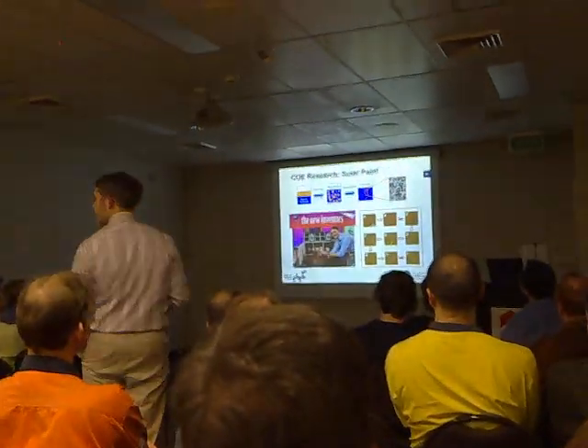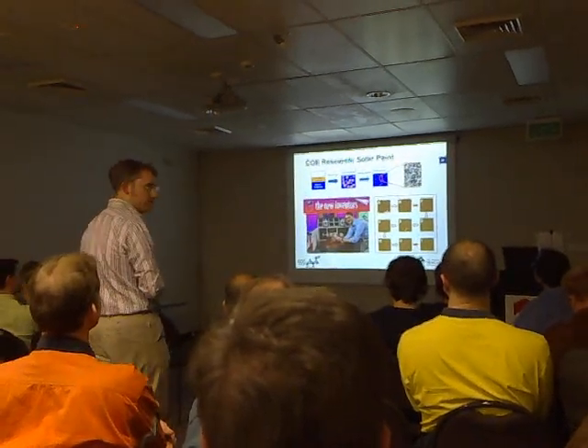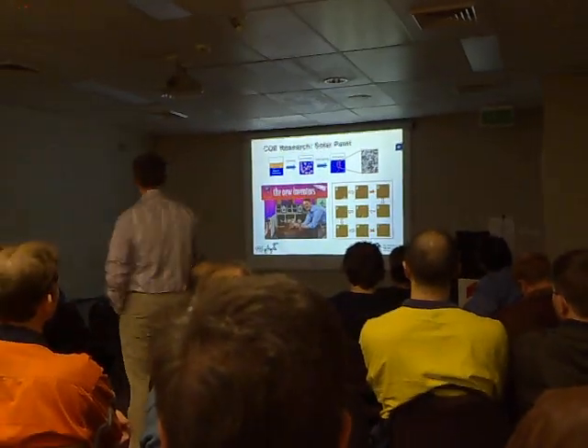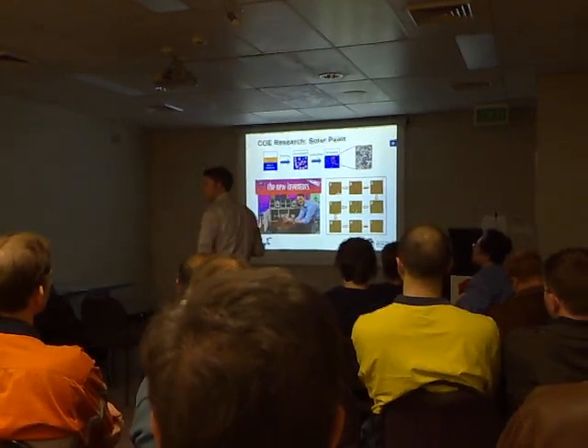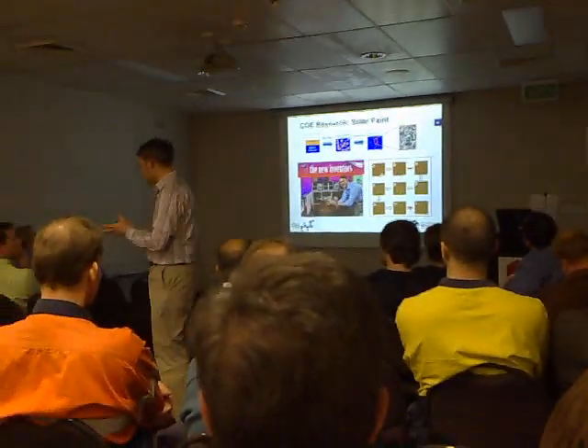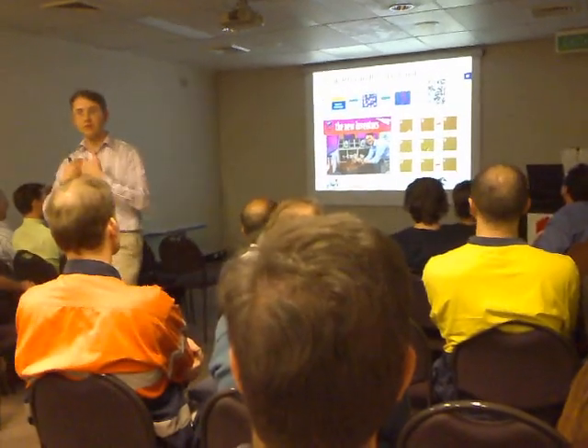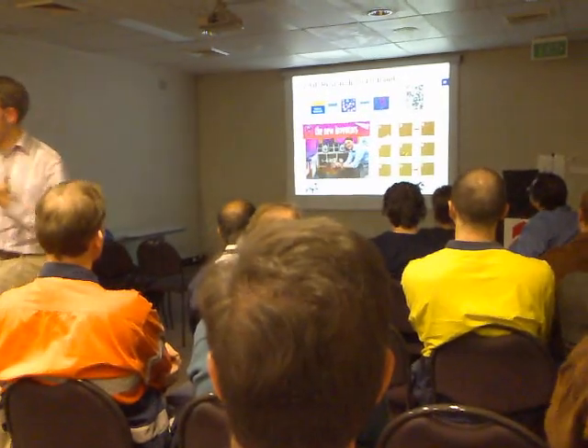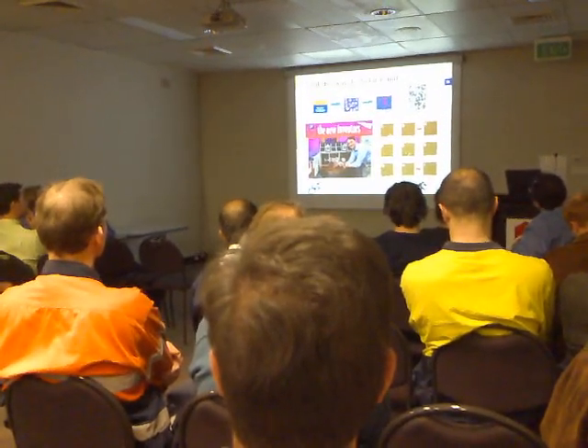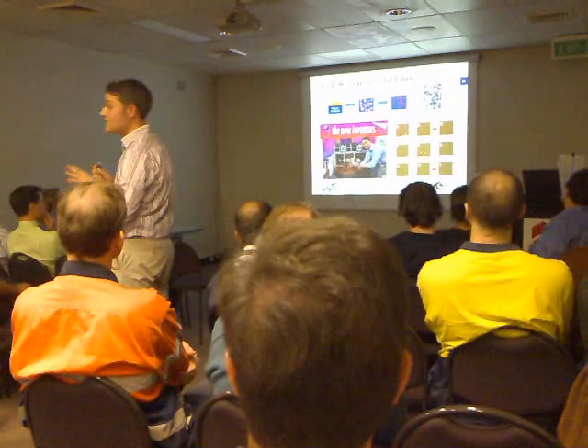But it turns out it can work. If we take our polymer dissolved in the organic solvent, put it over water and surfactant, stir it rapidly, and smack the hell out of it with a really high-powered sonic lance, we can create tiny nanoparticles suspended in water. We still use the organic solvent, but only to prepare the nanoparticles, and this reactor can be completely sealed — meaning we can recycle the solvent very easily. The thing we create is this water-based paint: tiny particles suspended in water. If we carefully layer these materials and carefully design the heating and drying steps, it turns out we can make really good solar cells.